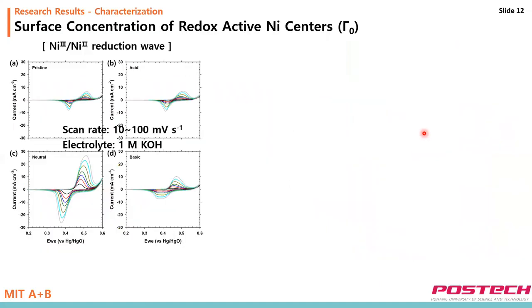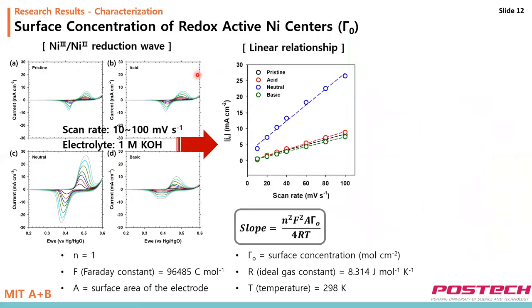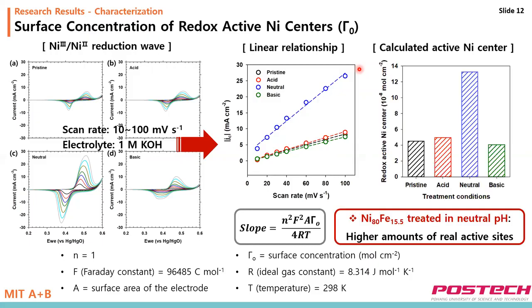Therefore, to find the reason for the increased UOR activity, I calculated the surface concentration of redox active nickel center. This value was extracted from the slope of the linear relationship between the peak current of the reduction wave and scan rate. Accordingly, the coverage of redox active nickel center has the largest value for the electrode treated in the neutral condition.